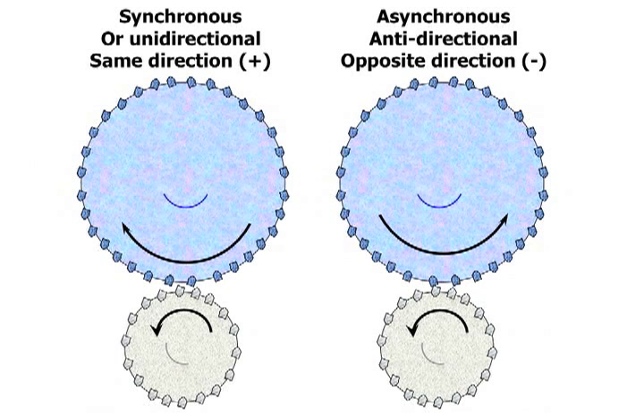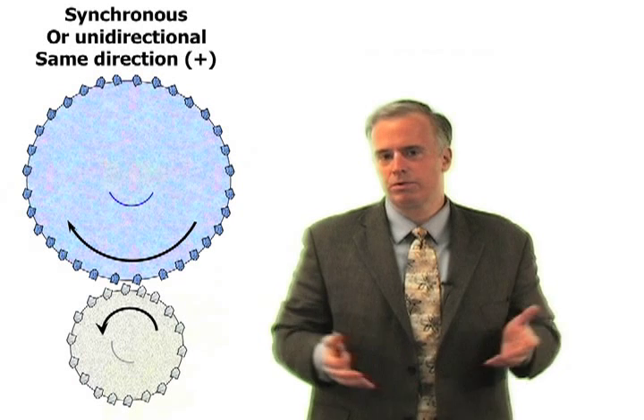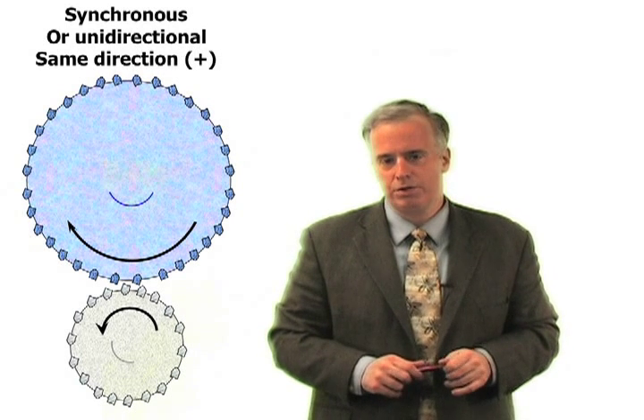So the solution was very simple. We just went back, changed the leads, went to the unidirectional mode, dressed the wheel, ground a few parts, the burn has disappeared, because we made the wheel sharp.